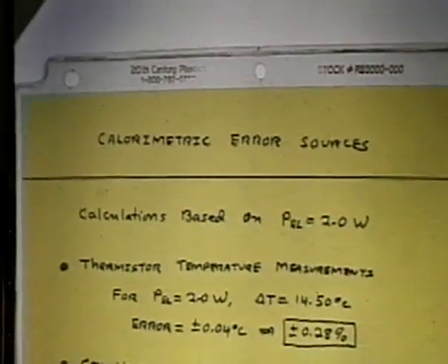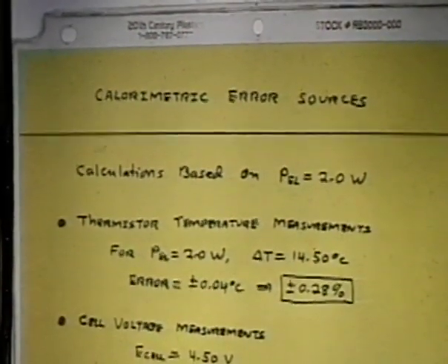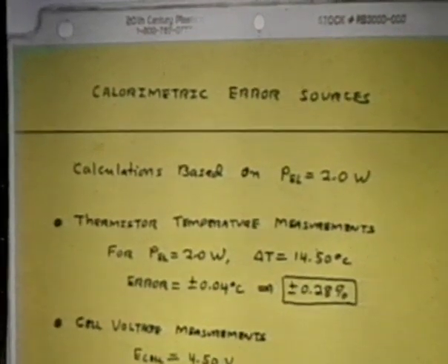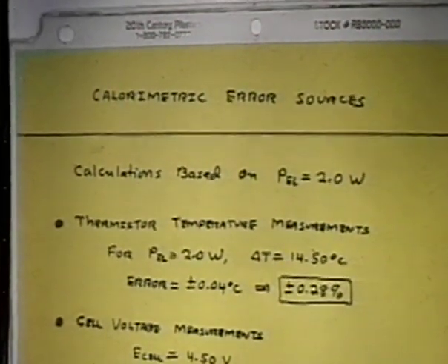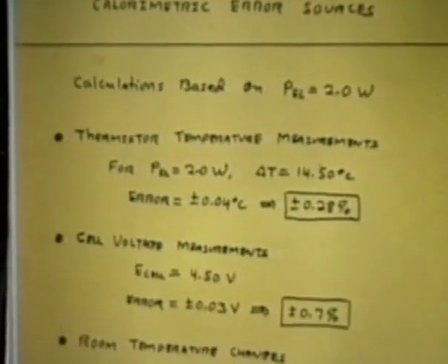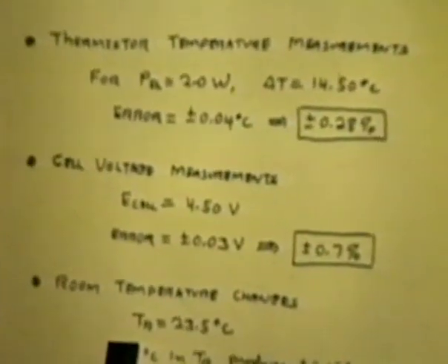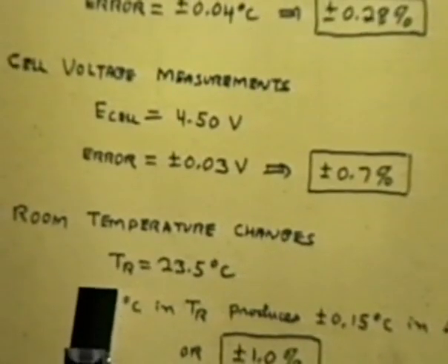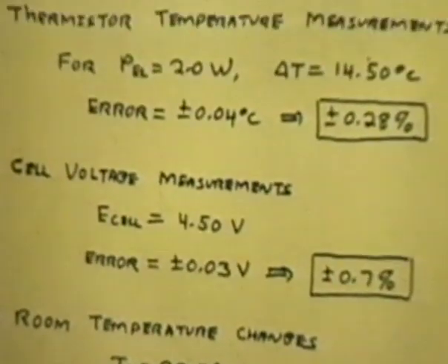This lists some of the error sources in the calorimetry. But as you see, the largest term here is the room temperature change. A 1 degree change in room temperature in our cell will produce a 1% error in the calorimeter. And that is about our error range today in our calorimetry of my design. We've got a newer design that's much better than that. I can measure to about plus or minus 20 milliwatts with this new design that his postdoc has developed. He's now getting accuracy of plus or minus 1 milliwatt.